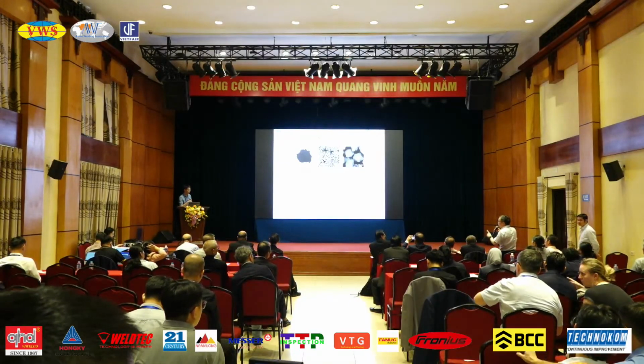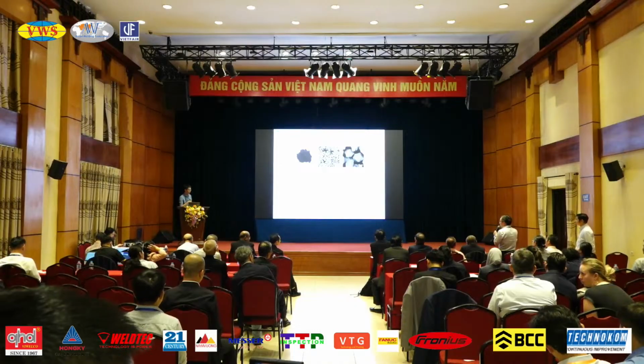Very good presentation. I have three suggestions. One, maybe the powder itself affects crack sensitivity heavily, according to my experience. If you 3D print pure tungsten, cracks easily occur. But I think the powder itself, made by different technologies, will affect this. The second one, you already mentioned in your PPT, is that tungsten alloy will reduce cracks. The third suggestion is that normally we use a commercial 3D print machine, and the temperature field is too steep, and the temperature decreases so quickly from the welding pool. If we modify the beam, maybe the result will be better.